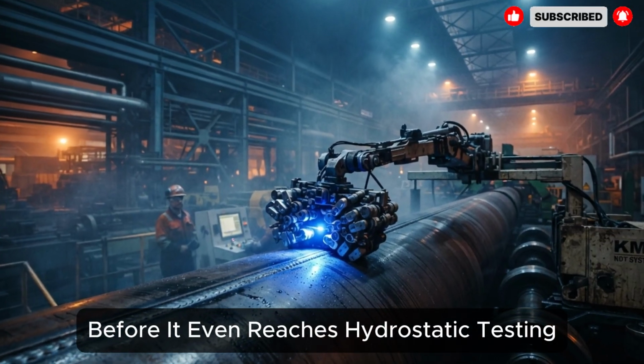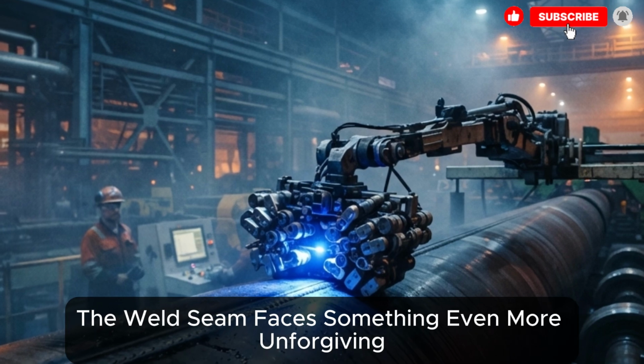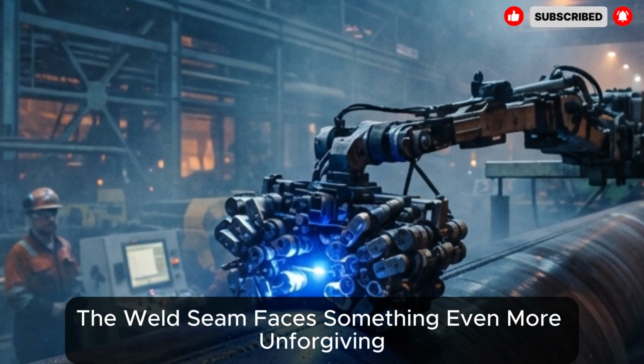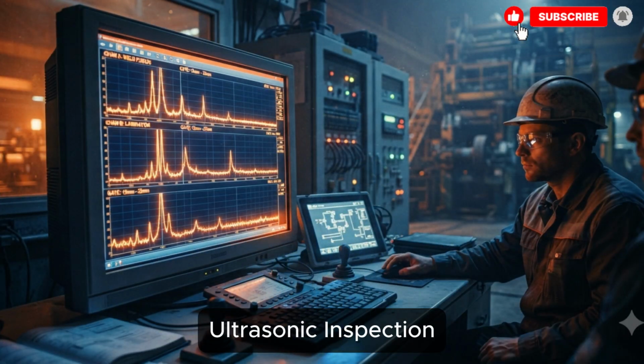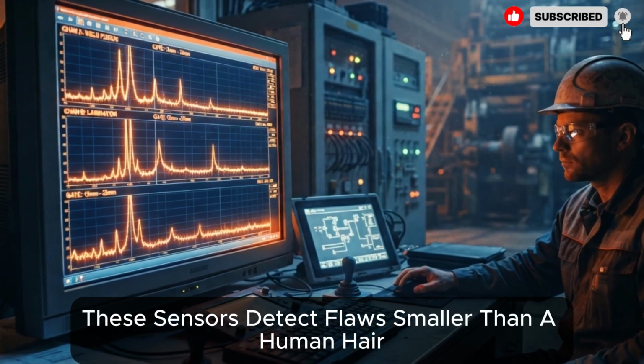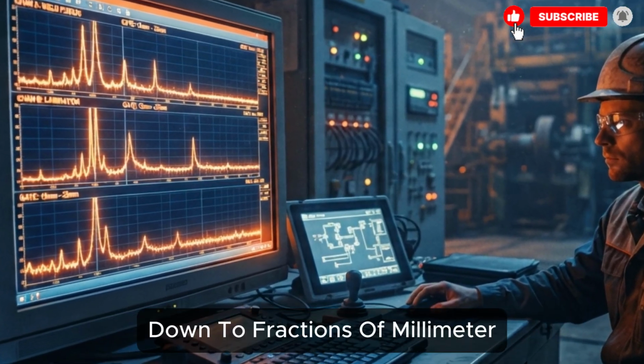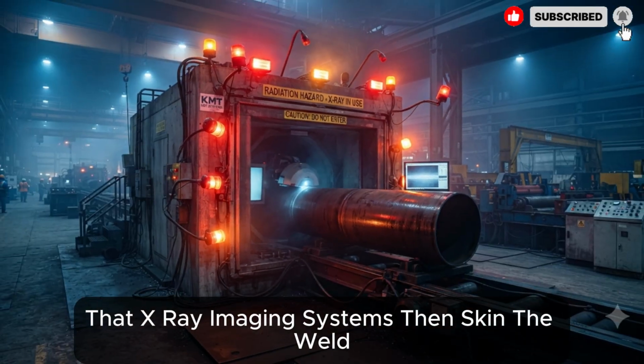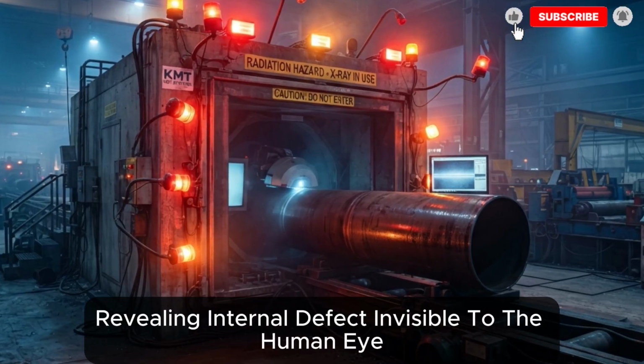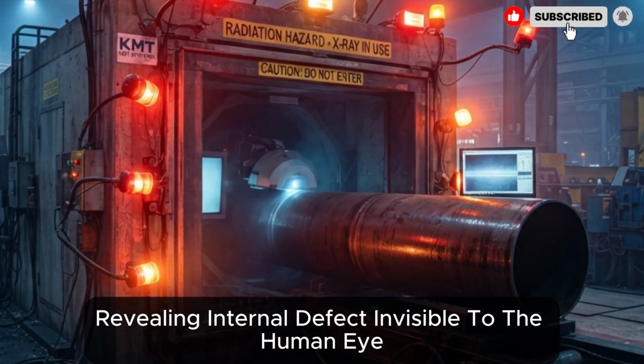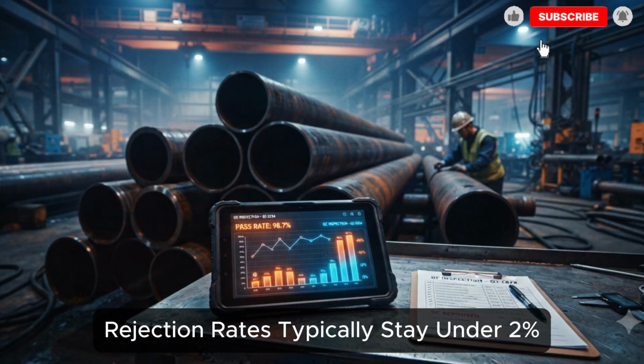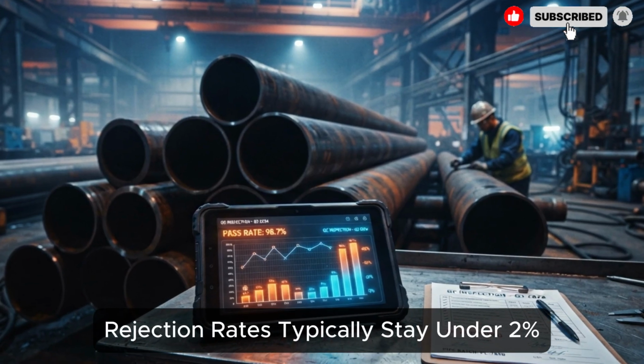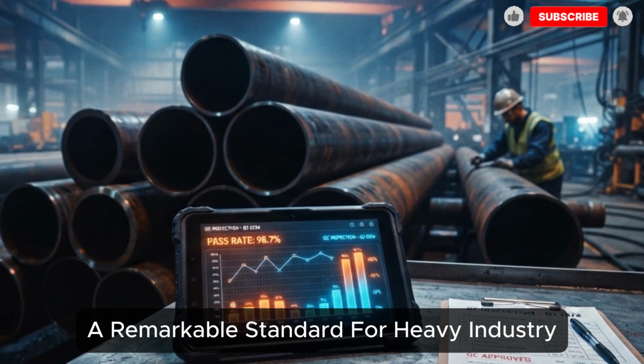Before it even reaches hydrostatic testing, the weld seam faces something even more unforgiving: ultrasonic inspection. These sensors detect flaws smaller than a human hair, down to fractions of a millimeter. X-ray imaging systems then scan the weld, revealing internal defects invisible to the human eye. Out of every batch, rejection rates typically stay under 2%, a remarkable standard for heavy industry.